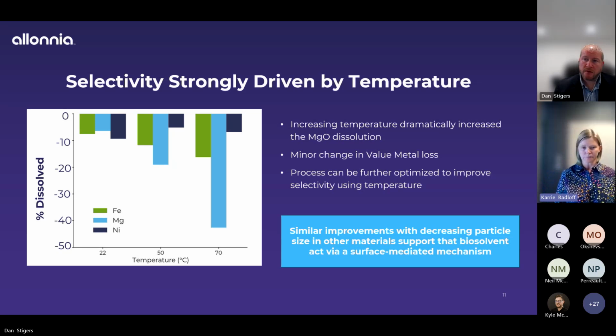One of the things we learned with these biosolvents, and in particular with this material, is that selectivity was strongly driven by temperature. So as we increase the temperature of the agitated leach, we're getting more magnesium dissolution, a little bit more iron dissolution, but that nickel is staying behind in the solid phase. This gives us that first indication that we can come up with process optimizations to also improve the selectivity and extent of the solubilization. We've seen similar results to this with other operational parameters. I won't have a chance to show all that data today, but in other mining materials, we see similar kinds of reactions based on decreasing particle size. So this all supports our understanding of how our biosolvents are behaving and interacting with these minerals.